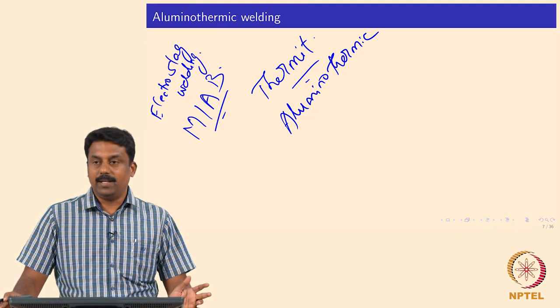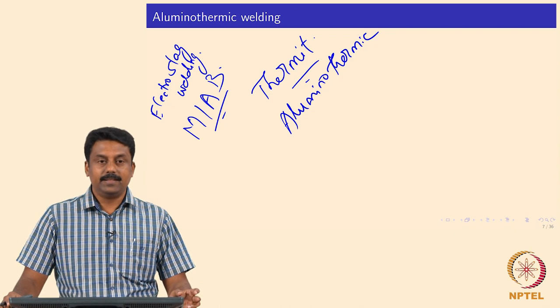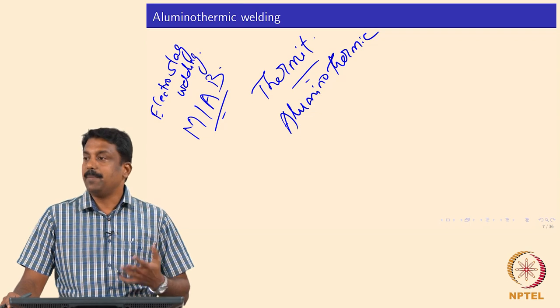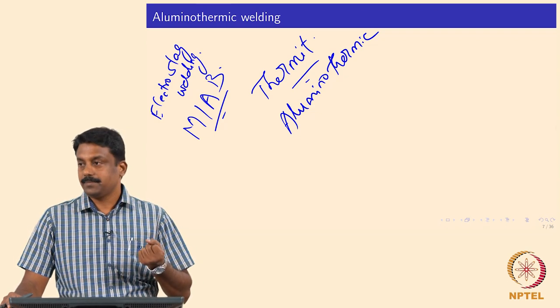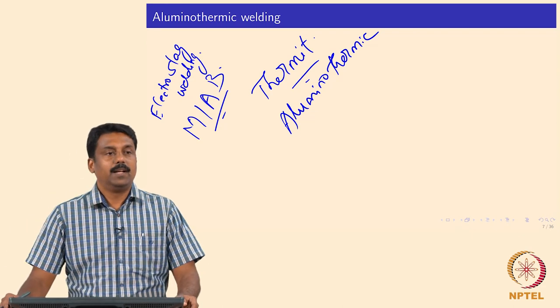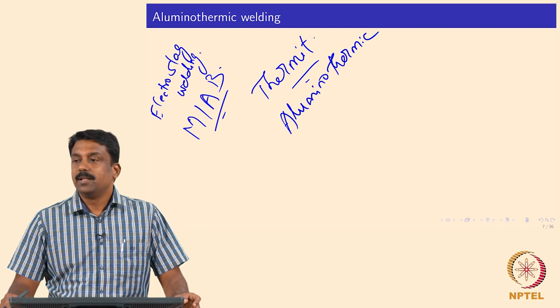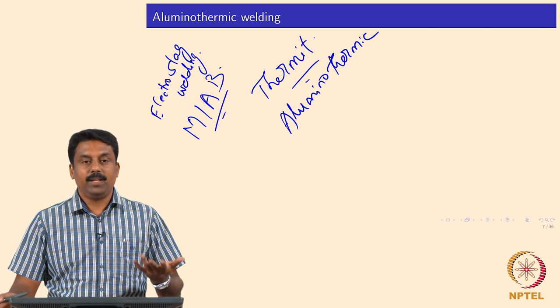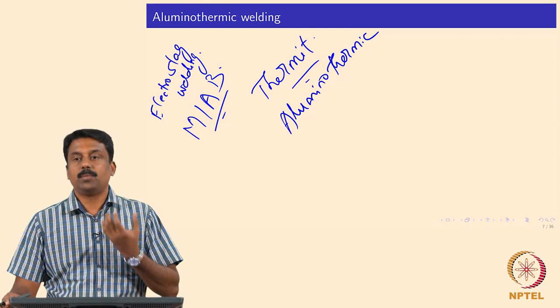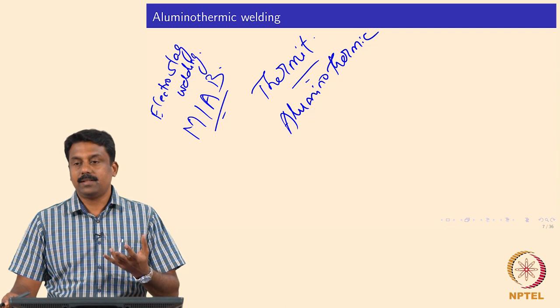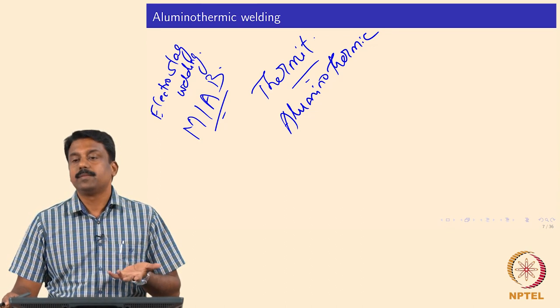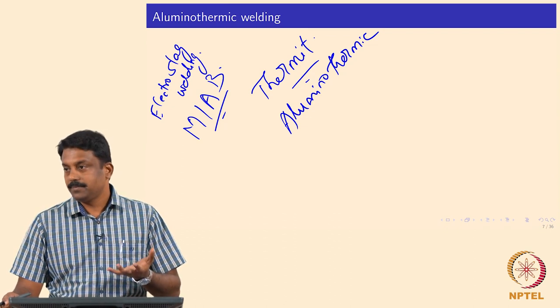The principle is that when a metal oxide is burnt with aluminium, the aluminium reduces the metal oxide and becomes aluminium oxide because of aluminium's high affinity for oxygen. Aluminium has a much higher affinity for oxygen than any other metal oxide. Aluminium oxidation is a highly exothermic process, so an enormous amount of heat is released. During this process the metal oxide gets reduced, producing molten liquid metal.